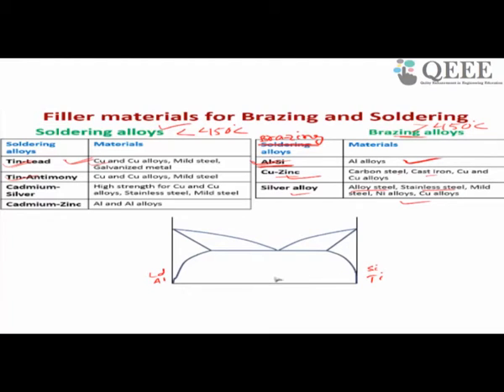What will happen in this case? It will have a pasty zone. This is the liquid, this is one solid phase, this is the second solid phase, this is liquid plus solid phase, this is liquid plus solid phase, and here you are getting alpha plus beta, two solid phases, and your braze or solder alloy should lie in this zone. This is called a pasty zone. So your alloy composition should be somewhere in this zone, liquid plus solid. So in brazing and soldering, the alloy should fall in this zone.